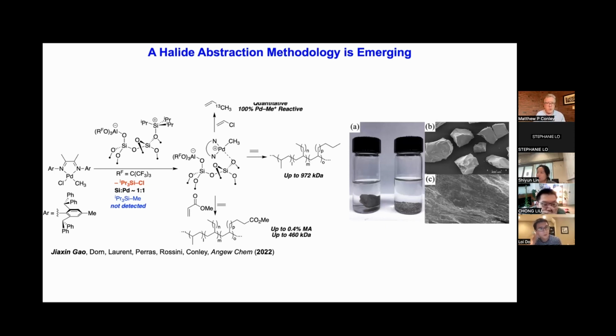Yeah, so MA incorporation with all of the supported single site palladium or nickel catalysts is always a bit lower than what you get in solution. Activity, again, if you go by mole product per mole metal, these are actually comparable to what you would get with the same catalyst in solution. Now, it's difficult to compare them side by side if you take them from the literature, but I think in this particular paper, we looked at this catalyst in our reactor, and we saw in solution and on the support, we had essentially the same activity.